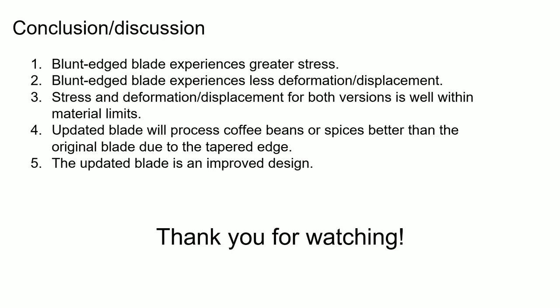It should be noted, however, the stresses observed in each case were well under the maximum yield strength of 207 megapascals for stainless steel, given by ANSYS material properties. Finally, the tapered blade design would likely produce a finer grind more quickly due to the smaller edge profile. This would result in the blade cutting through the material to be ground rather than pulverizing it with a blunt face.